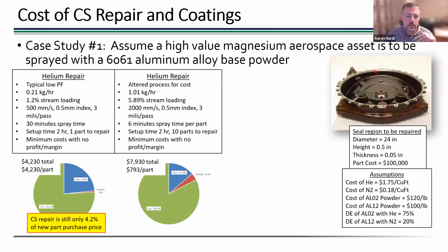And all of a sudden your per part cost goes down to $700, $800, right? But that also includes more parts in a lot, right? I assumed a 10-part lot here as opposed to a 1-part lot for the first case. So basically increasing the powder feed rate and then increasing the number of parts you spray gets you to this